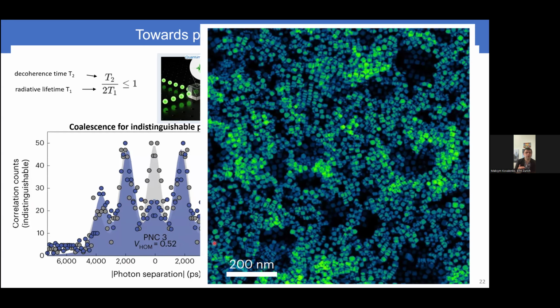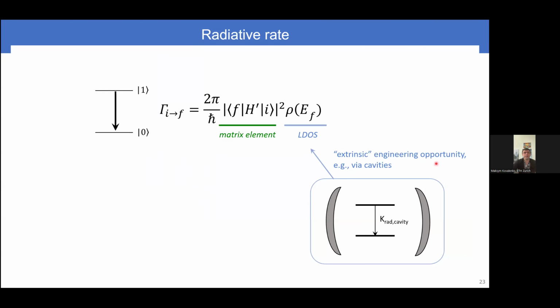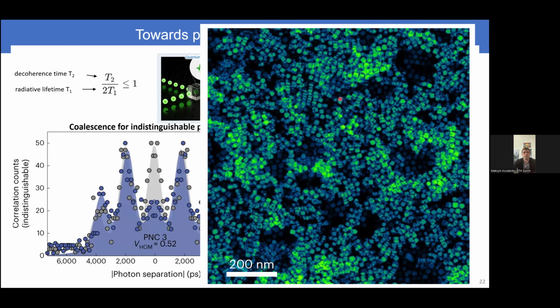And generally, as a chemist, you ask, and this is a TEM image of a sample, and of course, as a chemist, you ask yourself a question: what does govern these T1 and T2 numbers, right? And which of these dots, what size, what shape, are better suited for this, because you cannot really know that unless you are able to go and find that dot, which is nearly impossible. And so that leads you to look closer at these T1 and T2. T2 is really a mystery for now, and we don't know much about that, so we will so far discuss only T1. And so the way to approach that equality, this Fourier transform limit, is to make T2 as long as possible and T1 as short as possible.